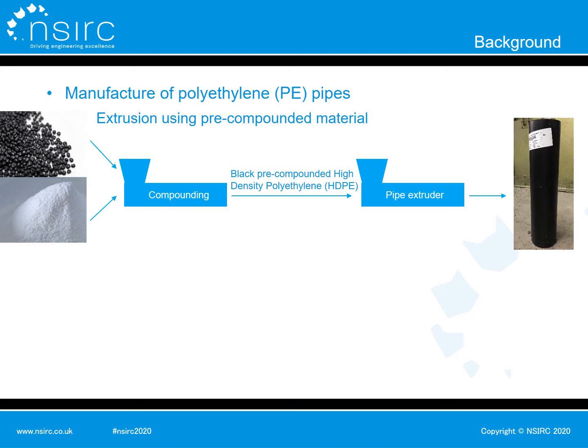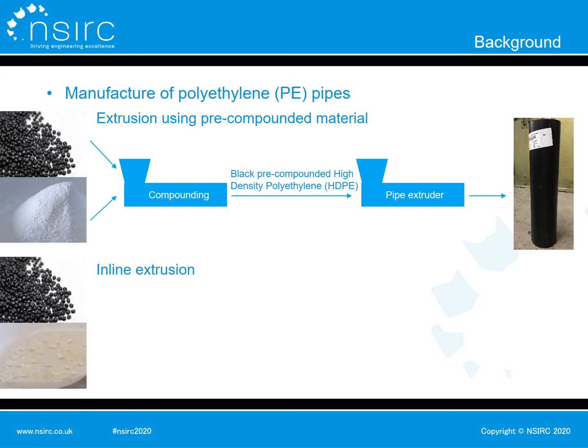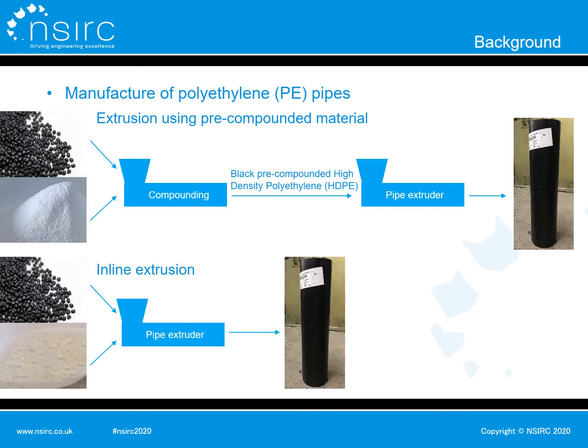carbon black and HDPE. Another manufacture process of polyethylene pipes is inline single-screw extrusion, in which a dry mixture of carbon black master batch granules and HDPE powders are fed into a pipe extruder directly to produce a black PE pipe. In this manufacture process, insufficient homogenization may occur because of improper screw design or using improper mixing elements.